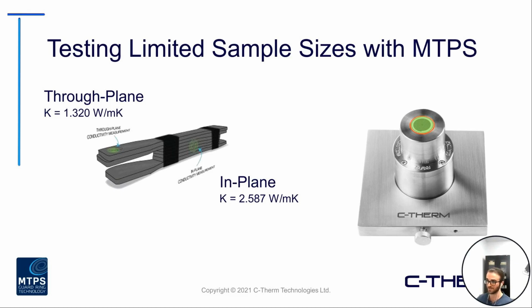The example on the right, you can see these tensile bars. Being able to take measurements in both the through plane and the in plane direction is possible, again, simply by how you're orienting the material on top of the sensor. And again, in this example here, we can see that there is quite a noted difference in the thermal conductivity along the different directions.